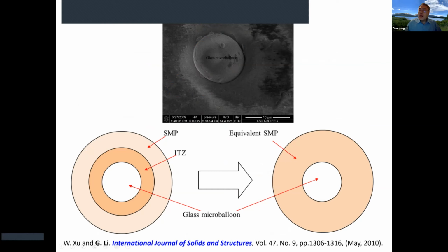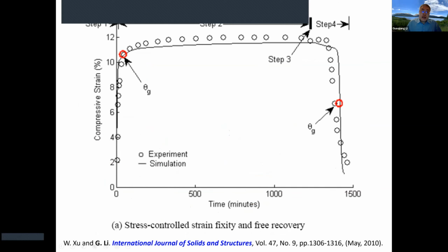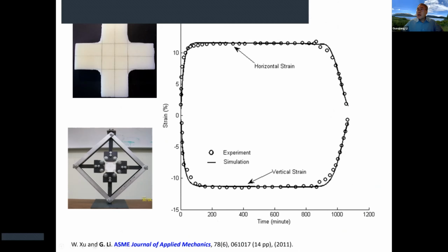All right, we also did some solid mechanics modeling. You can see this is basically the microballoon. You have an interfacial transition zone, and then you have the polymer matrix. So we can establish a three-layer built-in model, and then introduce viscoelasticity, viscoplasticity, and thermodynamics to model this polymer. You can see this strain change with time: loading, holding, removing the load, and then shape recovery. So the model can definitely reproduce the experimental result.